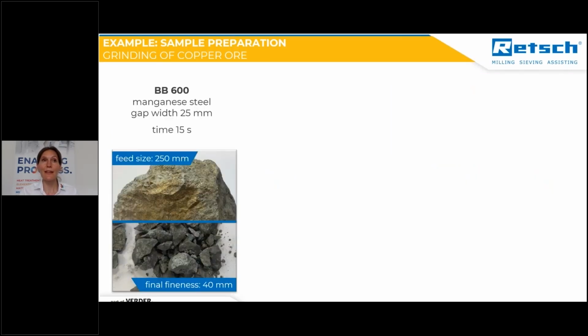let's have a look at the details. We used the BB600, which was equipped with jaws made of manganese steel. In terms of cross-contamination, you can also choose another material, for example, a steel for heavy metal-free grinding, or cast iron. And here we used manganese steel and chose a gap width of 25 millimeters. So in only 15 seconds, the material was crushed down to 40 millimeters.